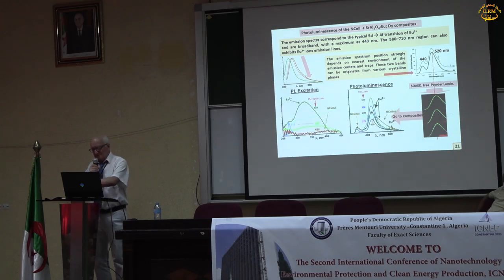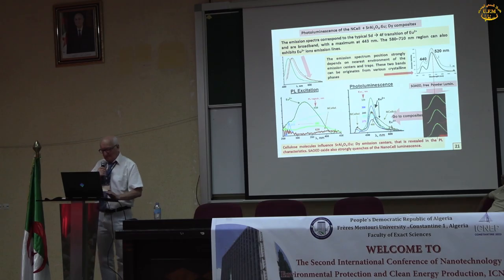Also, you see the luminescence of a composite of this oxide in the nanocellulose matrix. The luminescence is explained by the presence of two crystalline phases of this oxide. But we see that when we prepare the composite, the spectra change. So this is a revelation. The strontium aluminate oxide strongly quenches the nanocellulose luminescence, and this is a manifestation of the interaction between the cellulose matrix and the oxide.